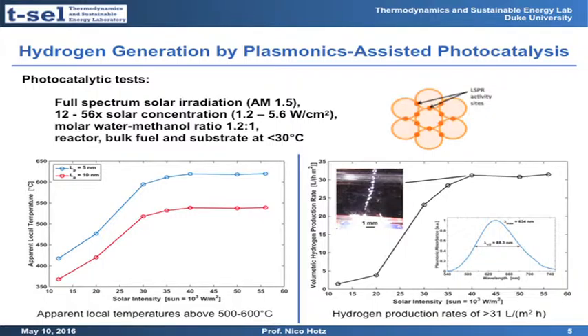hotspots. That's the number I said before of about 5 to 10 nanometer. We don't know exactly what it is, but it should be in the range of 5 to 10 nanometer, achieving these 500 to 600 degrees Celsius. A very important result here is we can achieve these high temperatures at solar concentrations of 30 to 40 times of regular solar light, which is very low, which can be achieved very easily in realistic systems.